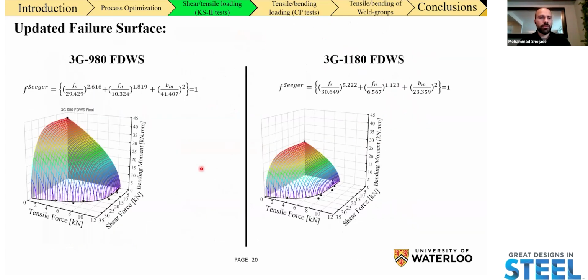Now we can update our 3D failure surface after performing the KS2 test. So you can see at the bottom plane here, we have more data points, and we actually have the optimized value of these exponents for the first two terms at least.